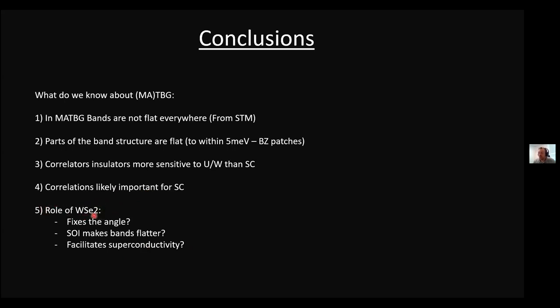So what is the role of tungsten selenide? There is one practical role: for us, it's a kind of secret sauce that makes everything work. Ever since we switched to tungsten selenide, we definitely have better control of the angle in our devices. But it could be that without tungsten selenide you can achieve the same thing if you are cautious enough. Spin-orbit coupling could make the band structure flatter, or at least parts of the Brillouin zone.